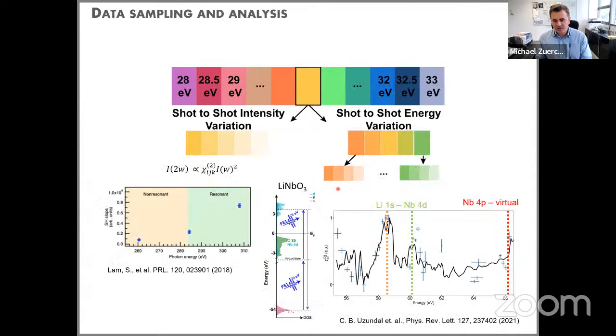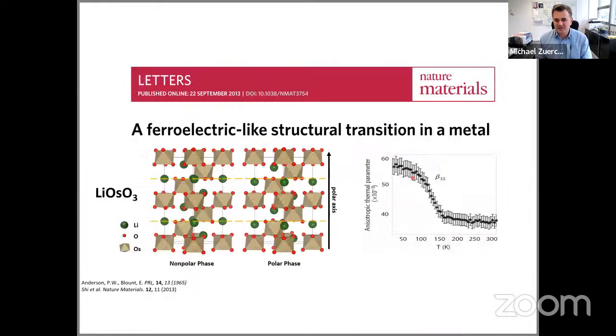So with this first work, where we also realized lithium is actually a nice target material at the K-edge to study, specifically with the free electron laser in Japan that outputs quite a high photon yield at, say, in this XUV range, we set out then to study the next system that we were interested in more from a physics perspective, and that is lithium osmate. So lithium osmate, shown here in the unit cell, is a ferroelectric-like material, but it's also metallic. And so that makes it quite interesting. It's also called a polar metal.